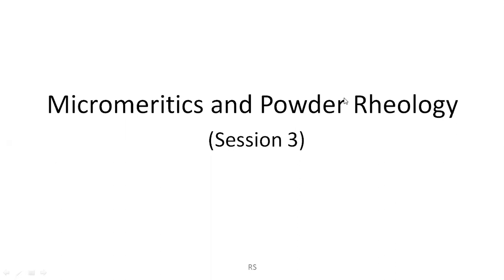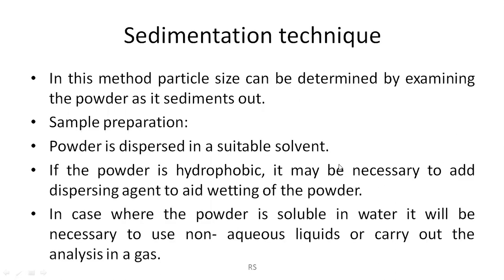First we discuss the sedimentation technique by which we can determine the particle size. In this method the particle size can be determined by examining the powder as it sediments out. For sample preparation, the powder is dispersed in a suitable solvent, and if the powder has a hydrophobic nature it may be necessary to add some dispersing agent to aid wetting. If the powder is soluble in water it is necessary to use a non-aqueous liquid or carry out the analysis in gas.